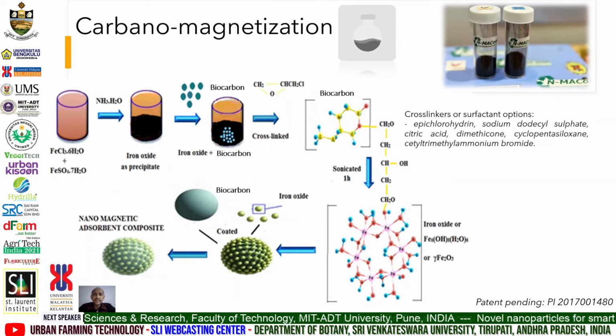Now, synthesis of our nanomagnetic adsorbent composite was achieved through a co-precipitation coupled carbonomagnetization method. The whole process actually can be done in a single stepwise procedure in open environment conditions. Simply put, this is a surface modification procedure where we allow the binding and attachment of iron oxide magnetic nanoparticles onto the biocarbon. The initial synthesis involved co-precipitation of the iron salts in aqueous solution under mechanical stirring. Ammonium hydroxide or sodium hydroxide can be used as the reducing agent, followed by a series of temperature and time-dependent sequential heating and mixing, ranging from 30 degrees Celsius to 80 degrees Celsius.